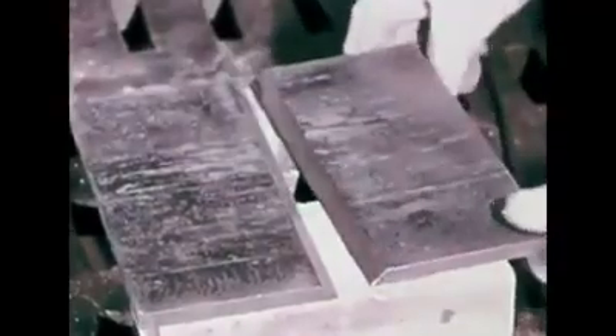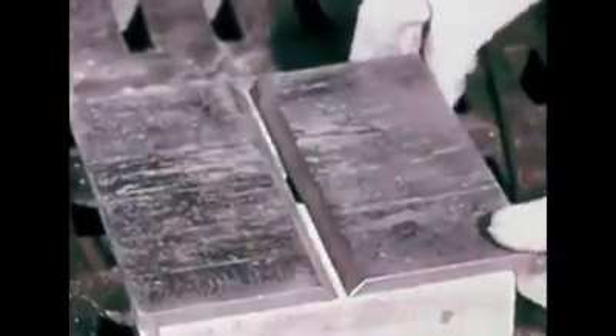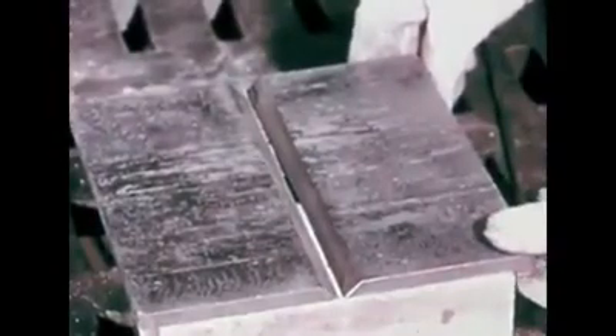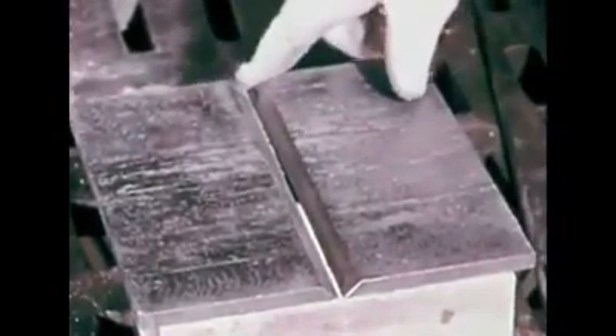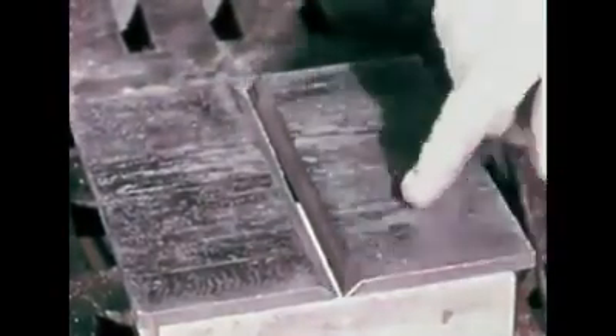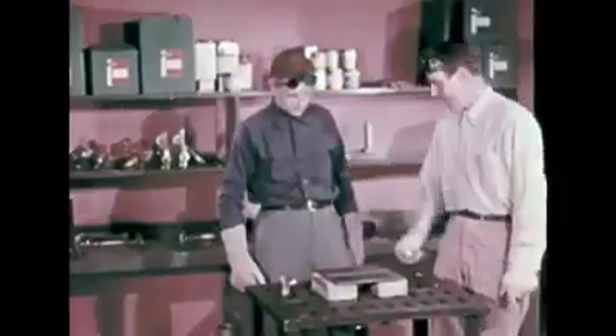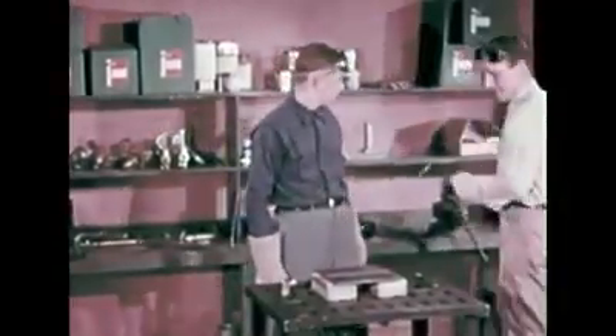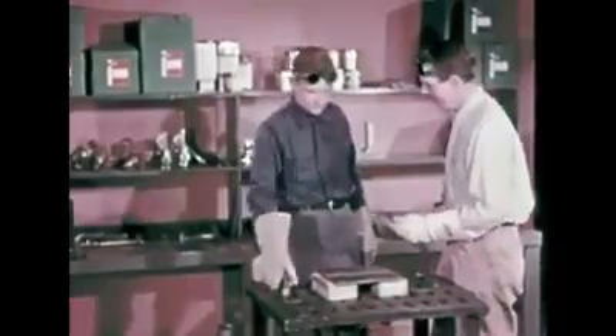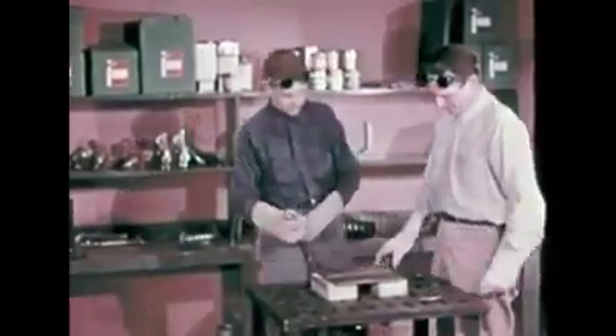This weld cross-section shows the complete blending of weld metal with base metal to form one solid piece. Let's try it. These plates have been beveled at the edges to form a 90-degree V. Because of the plate thickness, we will leave a 1/16 inch gap at the right side, widening to about 3/16 inch at the left. We will also use a larger blowpipe tip and a larger size of welding rod because we are welding heavier metal.